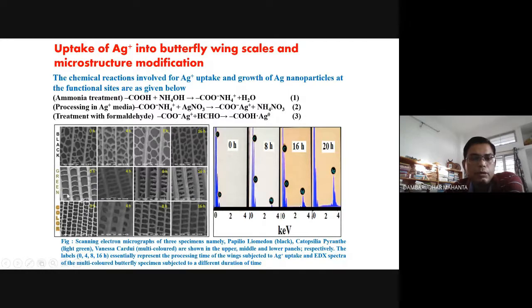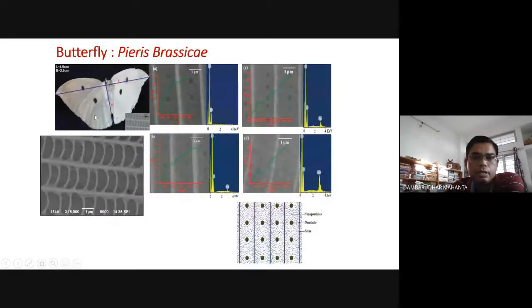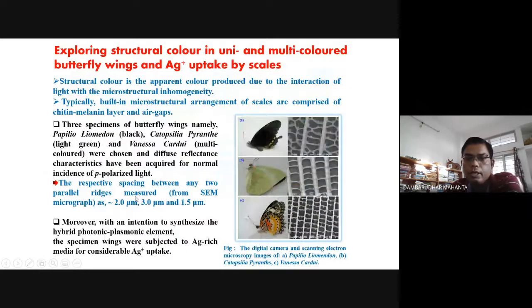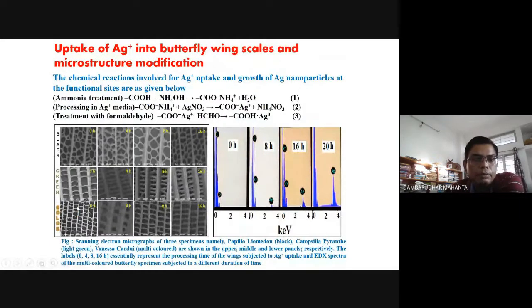So in this particular case, initially we started with the white butterfly. Then later we thought of working in multicolor, multivariant, starting from black, which is absolutely black, then weakly green, and another one is multicolor. In the same micrograph, you could see on the extreme left a black butterfly, green butterfly, then colored butterfly. Their structures you could see are very much different. In the first case, it is highly disordered. The pores are of different sizes in case of black, and that is why probably random scattering of light makes it appear black.